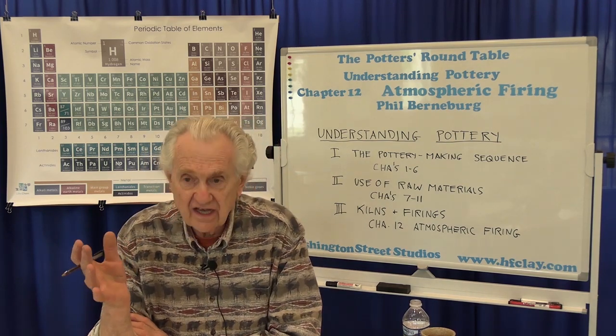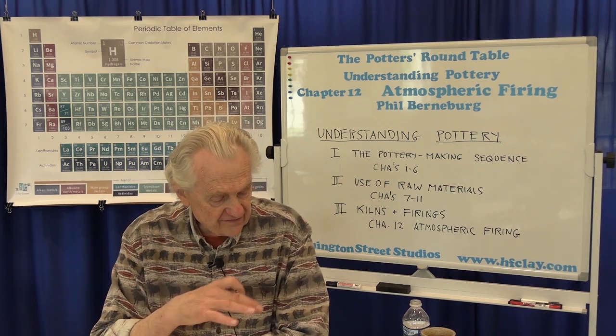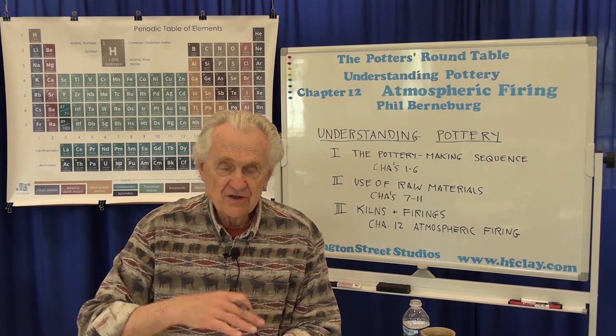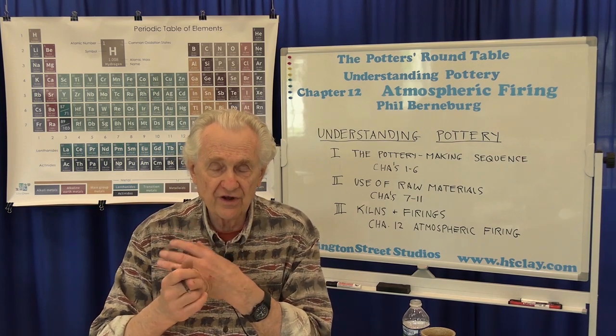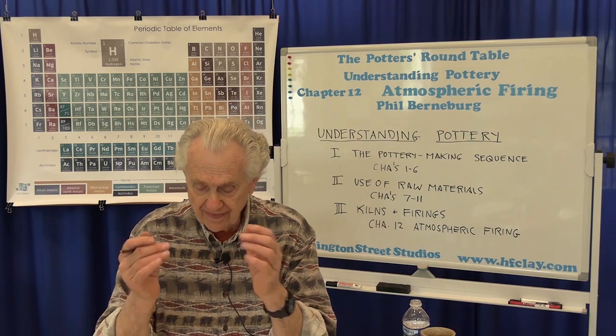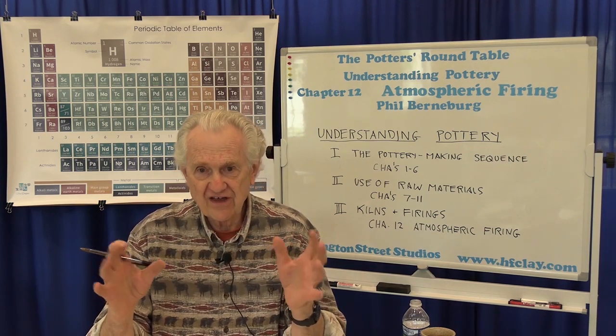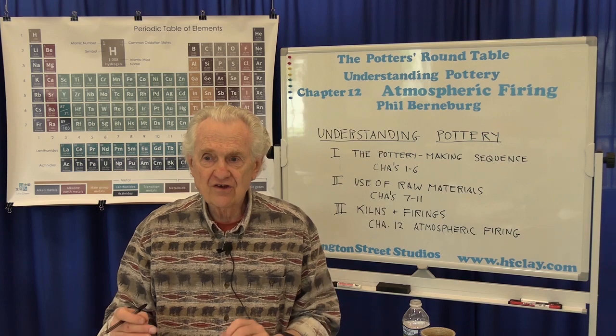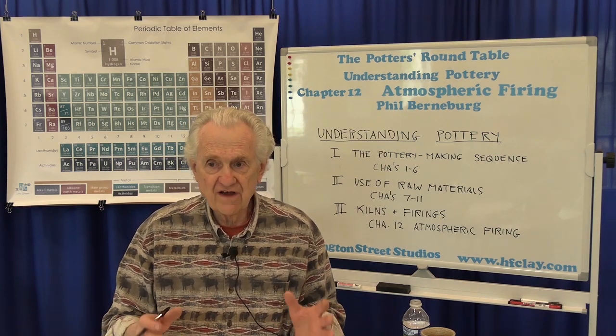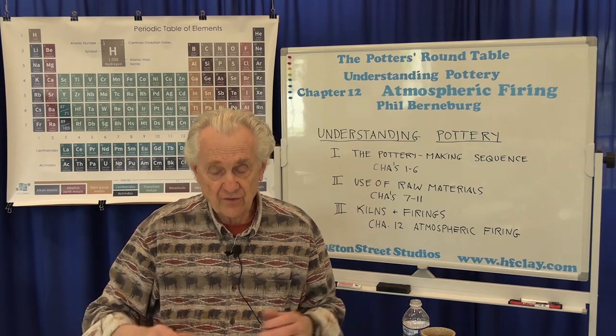In these last cases I haven't mentioned using soda or salt with electric firing — and you can't. You generally don't want to do reduction in an electric kiln unless you're doing it in an enclosed space, some kind of saggar. But also, the sodium would absolutely eat away the bricks and attack your elements and ruin your kiln. So both of these additions — the salt and the soda — are really confined to hard brick kilns and usually gas or wood.